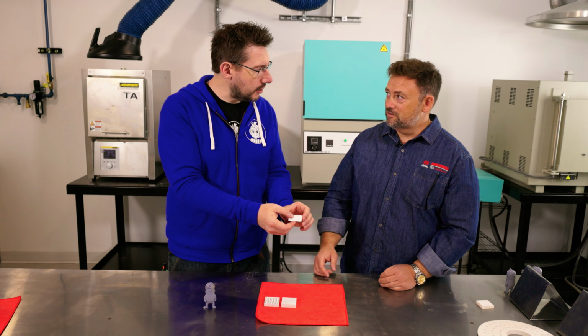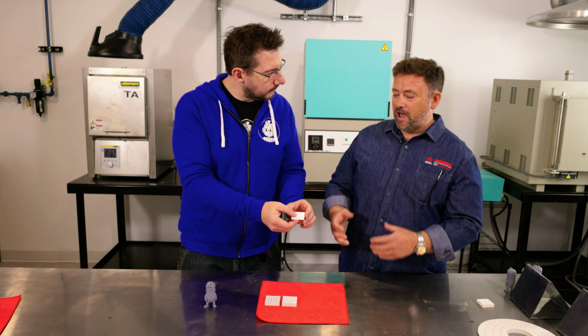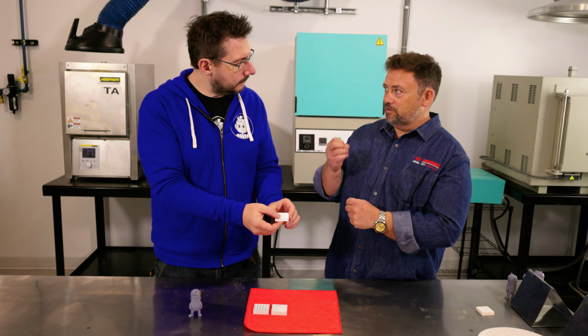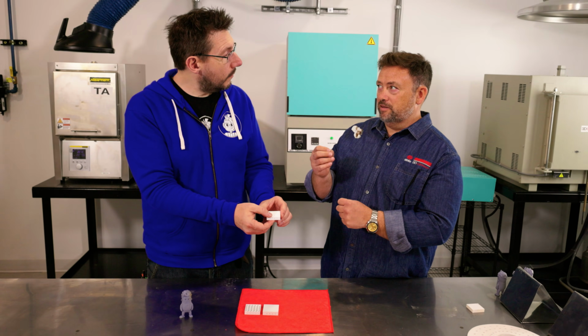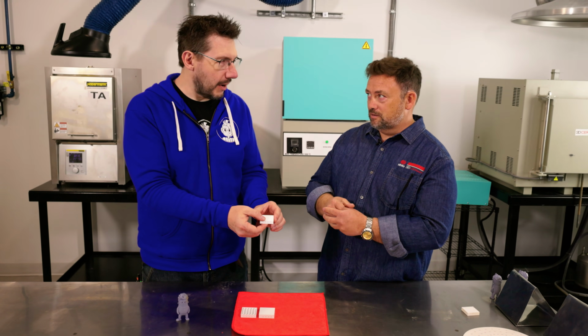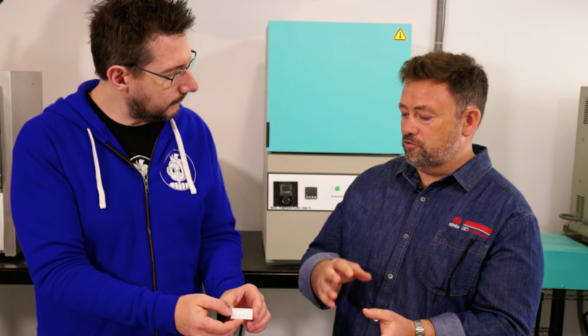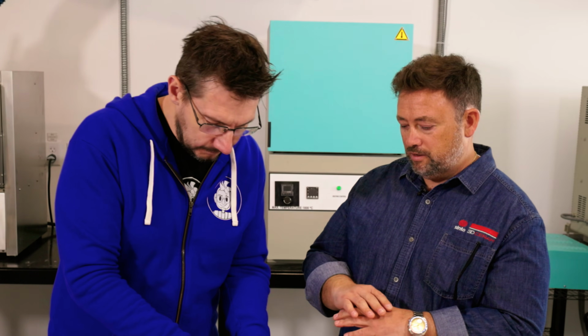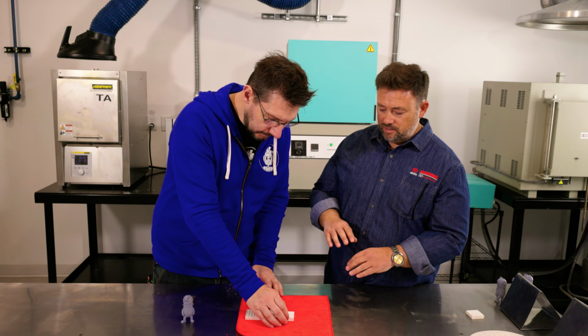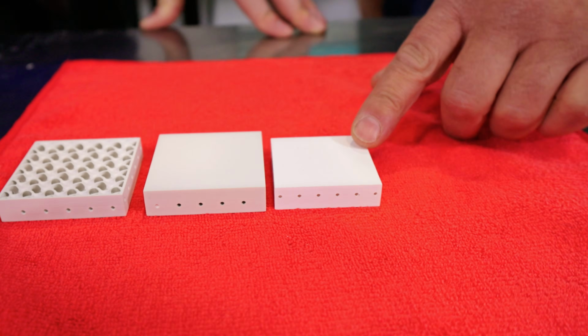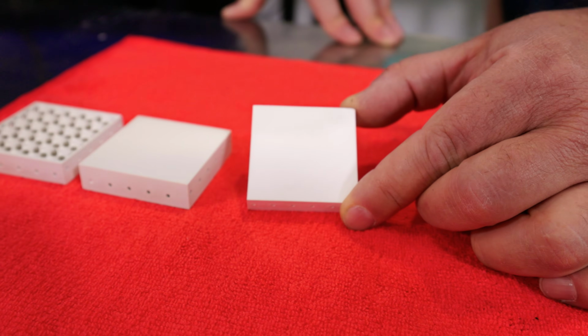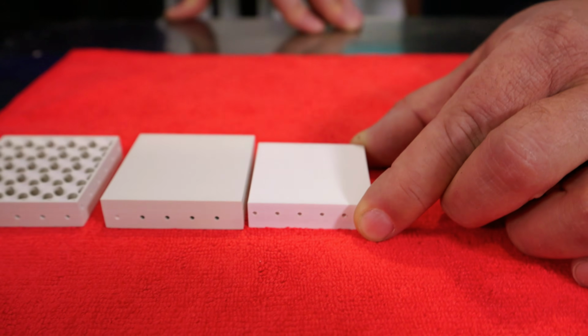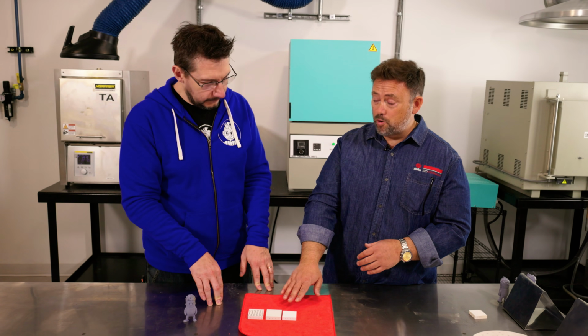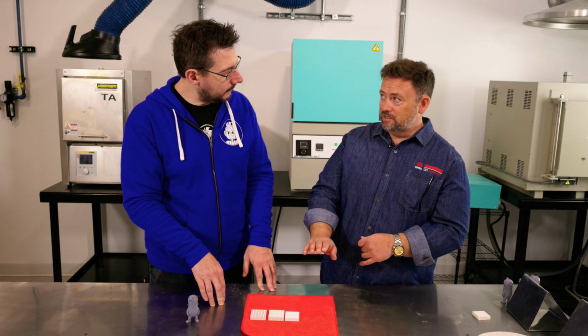Now, under nitrogen, why nitrogen? So the inert gas makes it so that you're not allowing oxygen in. The oxygen can also cause popping, a sudden pop, and the pop would cause a crack. That'd be very bad. So we want to keep popping and cracking to an absolute minimum, nothing. And then you'll see, as you go from A to B to C, this is quite a bit smaller. All of the resin is actually gone at this point. If it's white, there's no more resin, there's no more carbon, it's just ceramic.